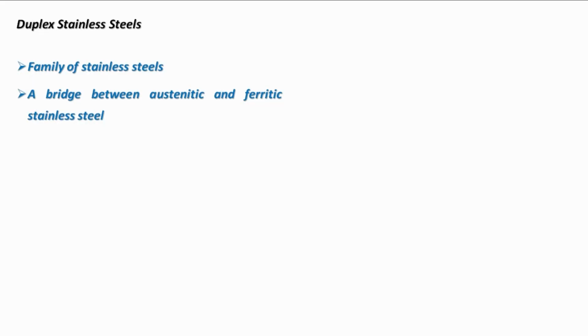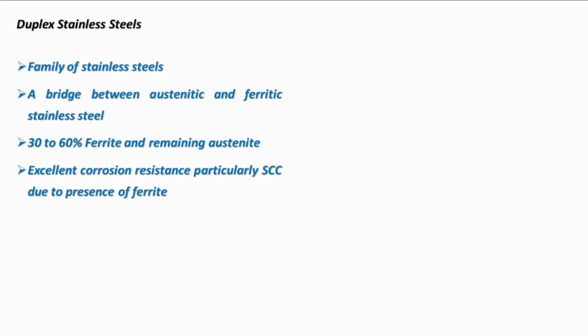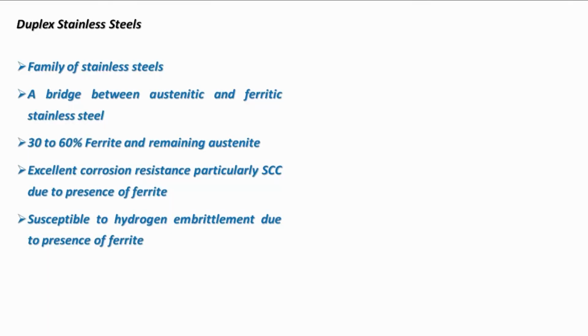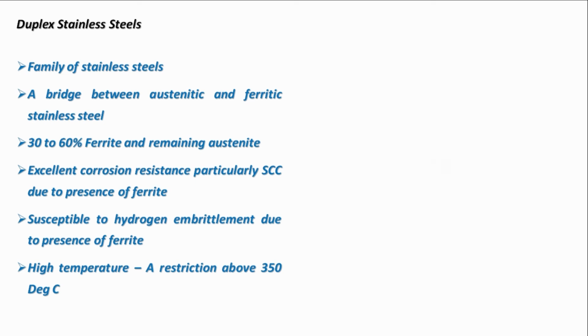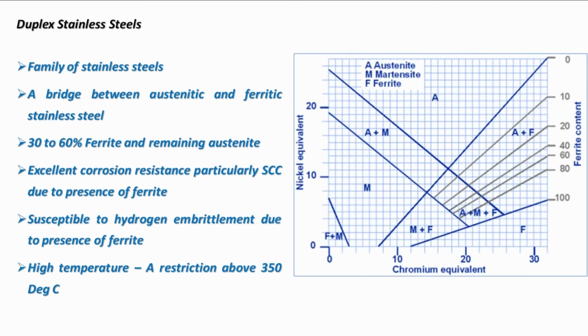Basically, duplex stainless steel is a family of stainless steel. It is a bridge between austenitic stainless steel and ferritic stainless steel. This material contains 30 to 60% of ferrite phase and the remaining austenite. It has excellent corrosion resistance to stress corrosion cracking due to the presence of ferrite. However, the same ferrite makes the material susceptible to hydrogen-induced cracking. So this material is restricted beyond an application temperature of 350 degrees Celsius because of the formation of various secondary phases that we will see in the upcoming slides.